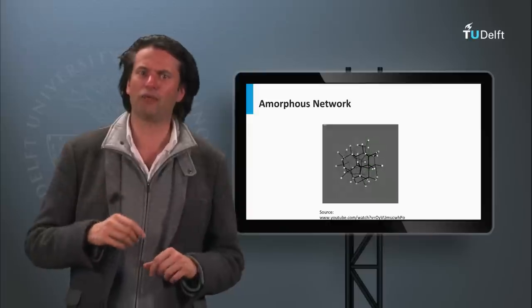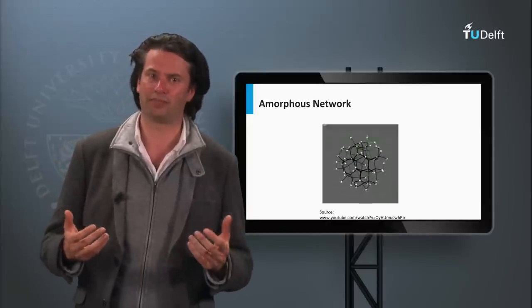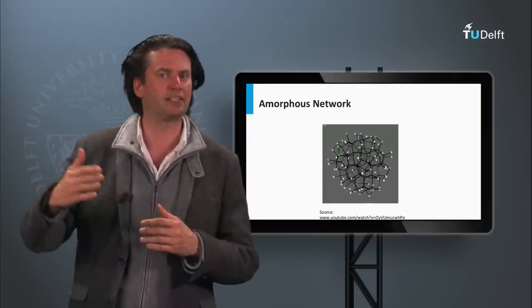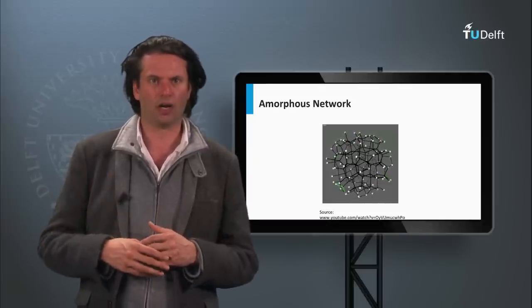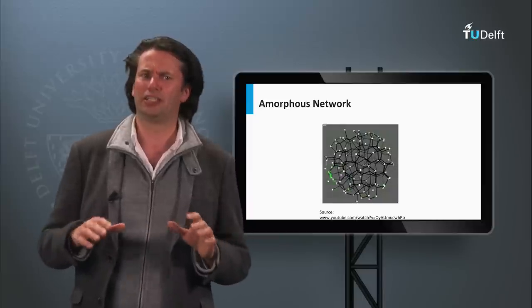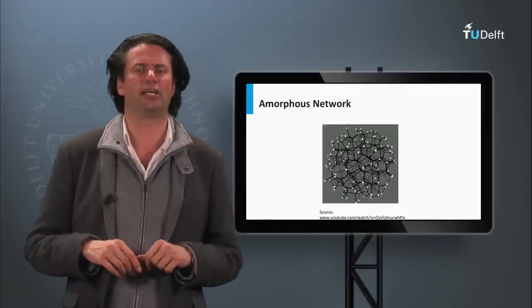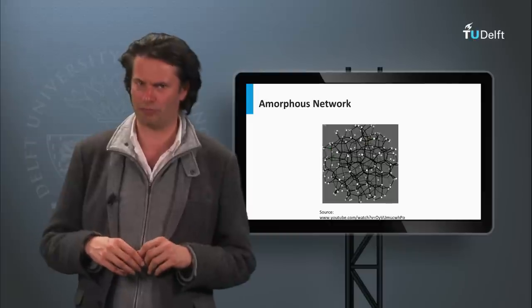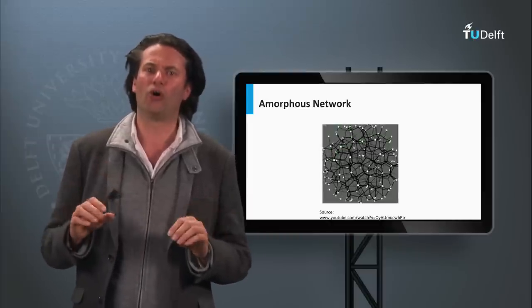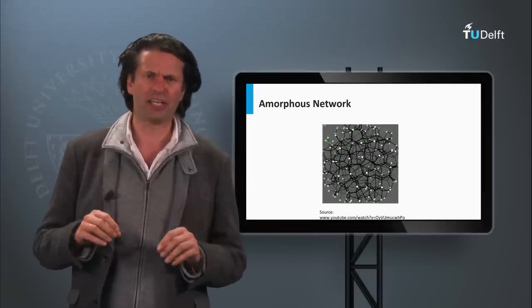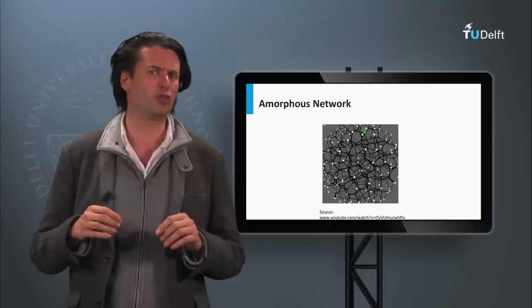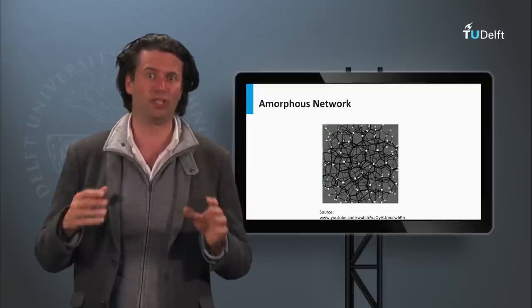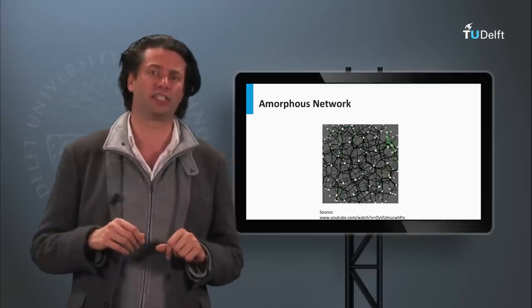Last week we discussed crystalline silicon, which has an ordered lattice in which the orientation and structure is repeated in all directions. For amorphous silicon this is not the case — the lattice is disordered, as shown in this animation. The animation shows the growth of a so-called continuous random network. On atomic length scales, also called short range order, the atoms still have a tetrahedrally coordinated structure, though the silicon bond angles and silicon-silicon bond lengths are slightly distorted relative to a crystalline silicon network.